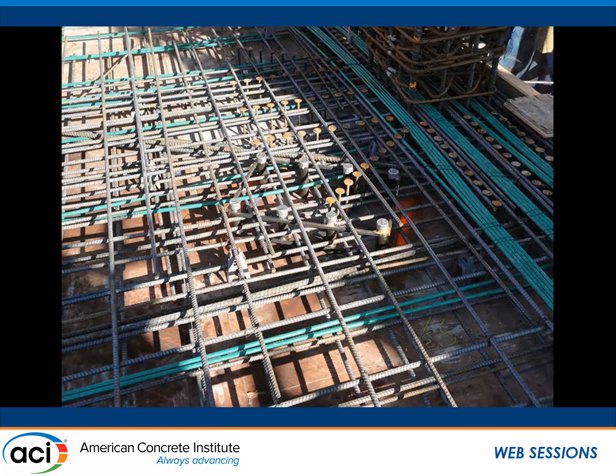Right here, I want to show a detail. After some recent testing in the industry, we found out that placing the stud rails works, especially when you're in a seismic region where you can get up to 2% drift in the buildings. You have to make sure that you don't get punching through the columns because of that drift. And what the research showed is that putting diagonal stud rails at the corner of the column is much more efficient and will perform much better than just using the traditional four-sided stud rails on the column.